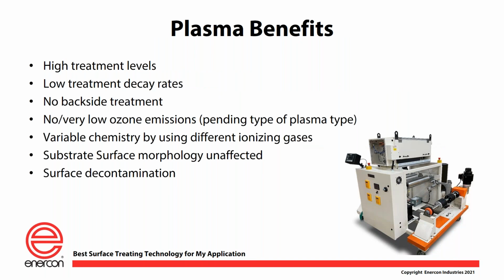So you can see here we have a plasma treater on this particular unwind/rewind in the image at the bottom right. Plasma treaters can provide higher treatment levels in some cases. They also can provide lower decay rates. Sometimes people talk about, hey, I treated this material, I got it to a given dyne number, a day or two later, the dyne level was reduced. Well, there's all kinds of reasons for that. Sometimes the plasma treater can't overcome those reasons. They're more endemic to the material than anything else. But nonetheless, it also can affect the longevity of a given dyne level and reduce its decay rate.